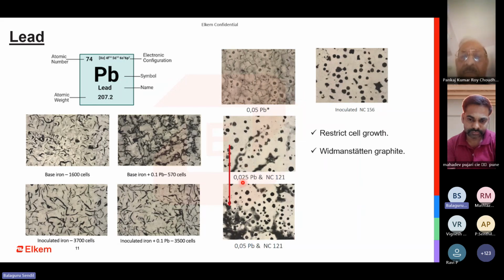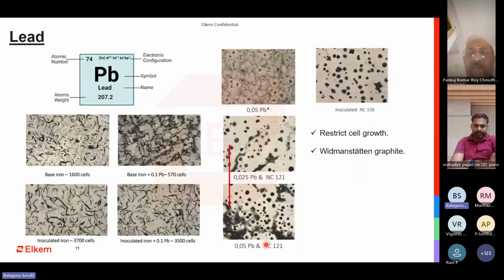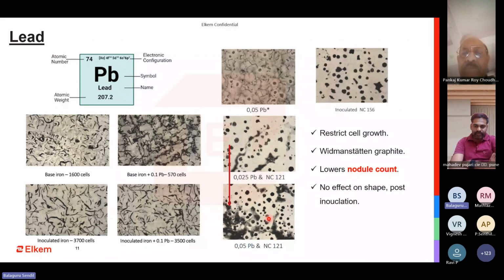This is what happens when I keep on increasing the lead content. If normally inoculated, I have 156 as my nodule count. At 0.025 lead, I have a drop in my nodule count. At 0.05, I am not seeing that much deterioration in my nodule count. So what it does is lower my nodule count, but it does not actually affect the shape post inoculation. If you have a high concentration of lead, the only thing you need to worry about is that the lead is not going to destroy the roundness of a nodule. It is only going to reduce the number of nodules available. As you keep increasing the lead, the number of nodules available will decrease, and it also promotes pearlite. So this is what lead does.